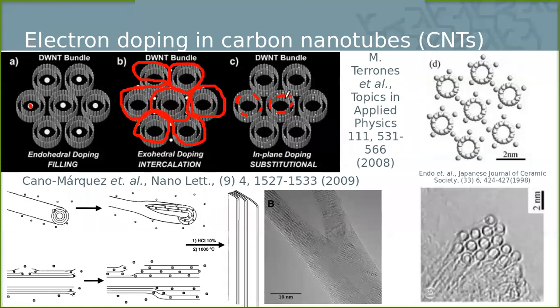The first people who tried this kind of in-plane or interlayer doping found an interesting result, because they wanted to dope the material, but at the time that they were doping, the atoms started to enter the planes of the carbon nanotube, and they started to break the carbon nanotube, and they created what is now called multiple carbon nanoribbons, or nanoribbons of graphene, by integrating these alkali metals in between the layers that break the structure of the carbon nanotube and create these long layers of carbon material.